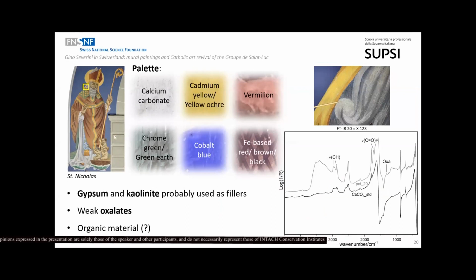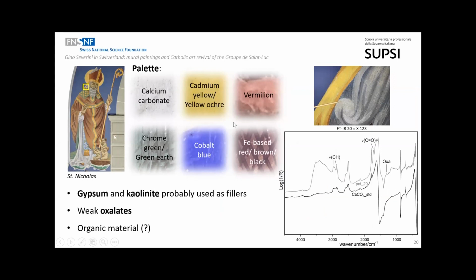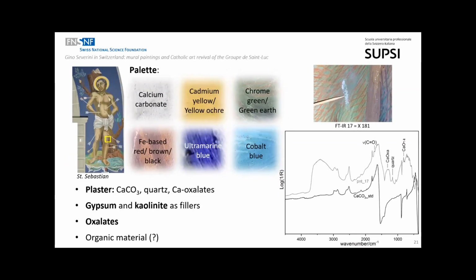Concerning the figures of St. Nicolas and San Sebastian on the triumphal arch, the palette and the pigments are limited compared to the others analyzed for the Trinity or Eucharist scene. In this case, the technique used is fresco, and this also explains the limited palette used by the artist. Here and also in the San Sebastian, in fact, the presence of an organic material is not clear. It is possible that Severini mixed with the pigment a very small amount of organic materials, but we are not sure.